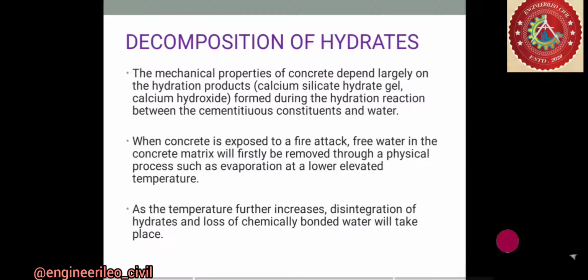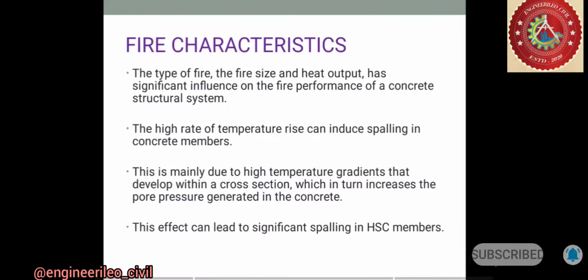The type of fire, the fire size, and the high heat output have significant influence on the fire performance of a concrete structural system. A high rate of temperature rise can induce spalling in the concrete members. This is mainly due to the higher temperature gradients that develop within a cross section, which in turn increase the pore pressure generated in the concrete. This effect can lead to significant spalling in high strength concrete.